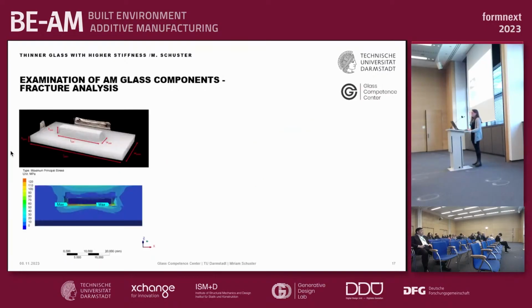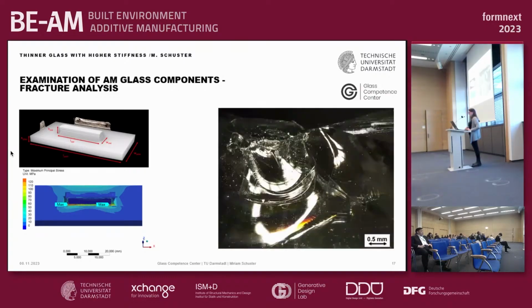Then we are also able to produce some digital twins of the actually printed samples. Those digital twins can then be used for finite element analysis in order to determine the maximum stresses, for example. And after breakage, we also looked at the fracture mirror in order to check where the fracture origin was.